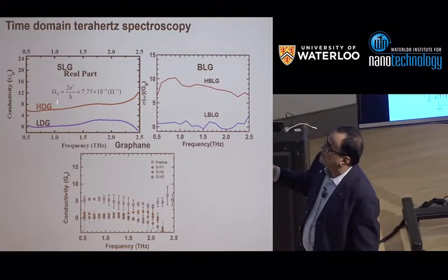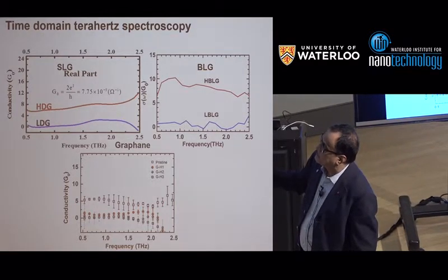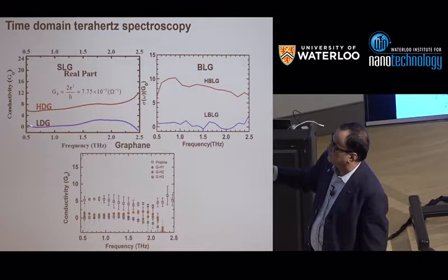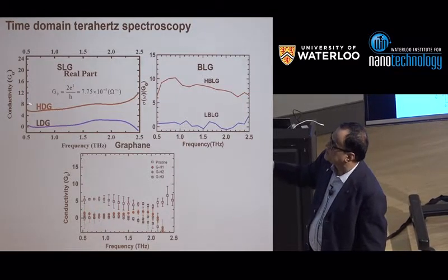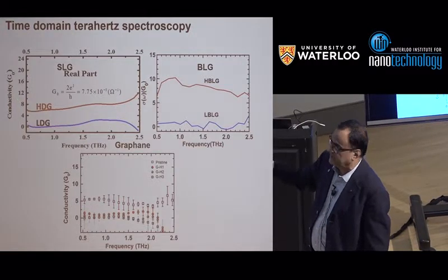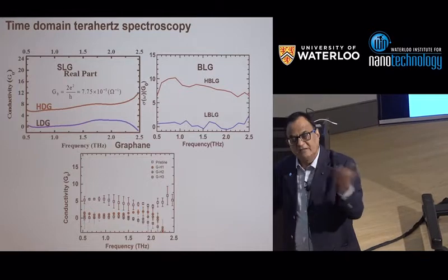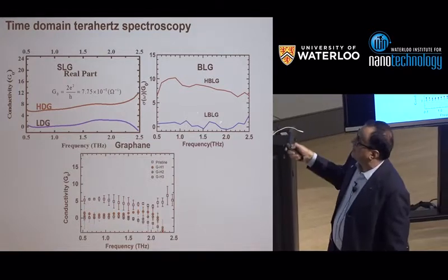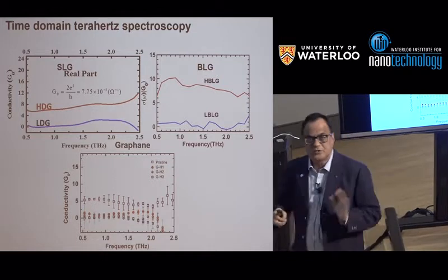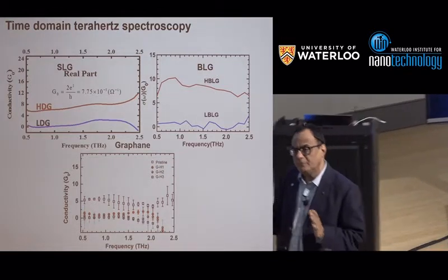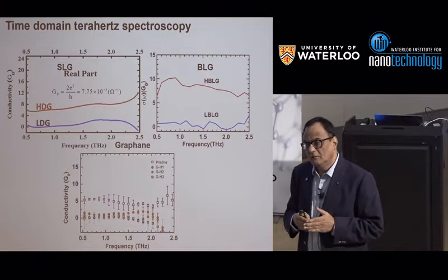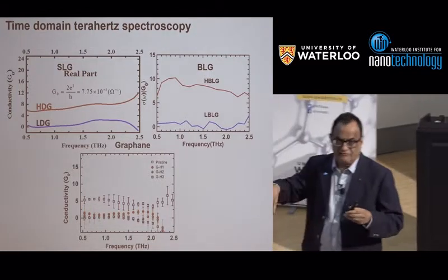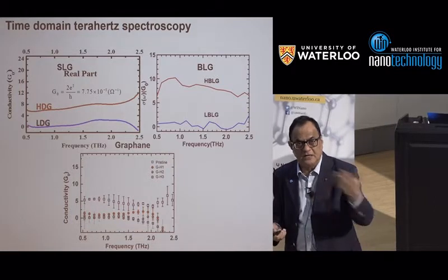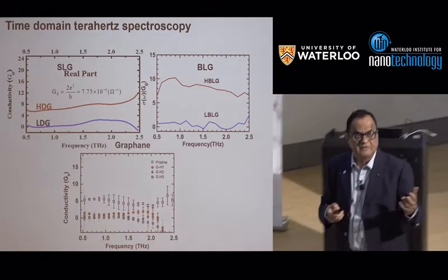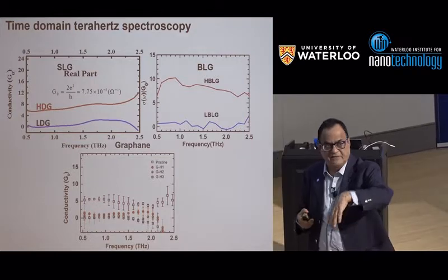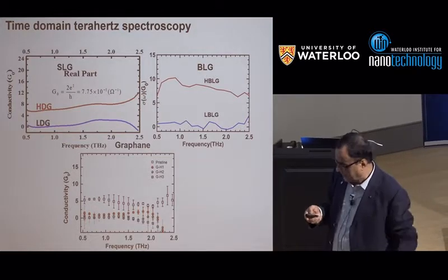So you can make single layer graphene with different dopings and measure the real part of conductivity as a function of terahertz frequency. You can see high conductivity and low conductivity by varying the carrier concentration in a variety of ways. You can do it for bilayer graphene too. Once we know these samples, of course, this technique is very powerful and is used in industry now for making the conductivity map of graphene. This is quite a standard thing in the last few years. The spatially resolved terahertz conductivity is a good measure of graphene quality.